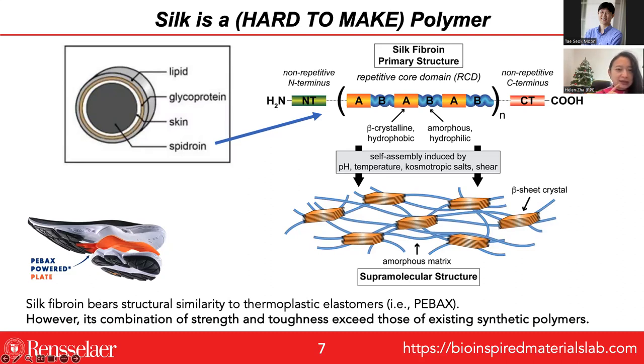And if you look at the sequence of these spidroins or fibroins, you'll see that they look a lot like a polymer. So they have a very large repetitive central core domain, which has these AB blocks that repeat over and over again. The A blocks in this case would be hydrophobic and tend to form beta sheet nanocrystals. The B blocks are very amorphous and usually pretty hydrophilic, and they're often high in glycine, proline, and glutamine content. There are terminal, N-terminal and C-terminal domains that are more or less helical. We'll talk a little bit about them later, but for the most part, this central core domain dictates the properties of the silk.